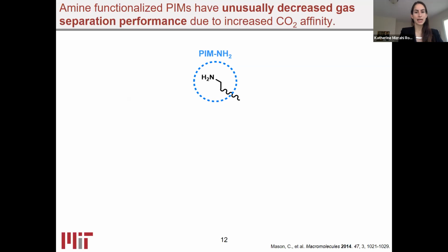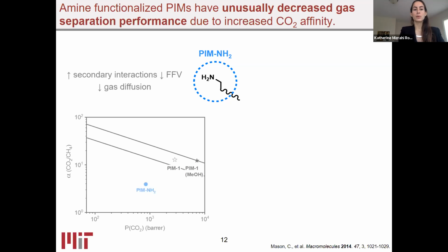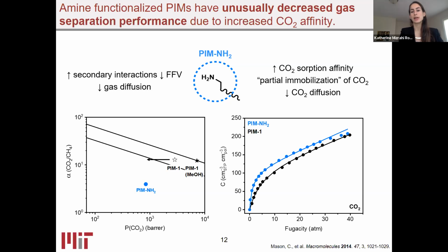So we looked specifically at amine PIM1, not because it had the worst performance, or not only because it had the worst performance, but also because it had the chemistry that would allow us to carry out the synthetic platform that we wanted to carry out. On one hand, amine PIM has secondary interactions that lower fractional free volume and reduce gas diffusion. And on the other hand, the amine PIM also has very high sorption affinity, which unusually partially immobilizes the CO2 and further reduces gas diffusion and CO2-based performance.